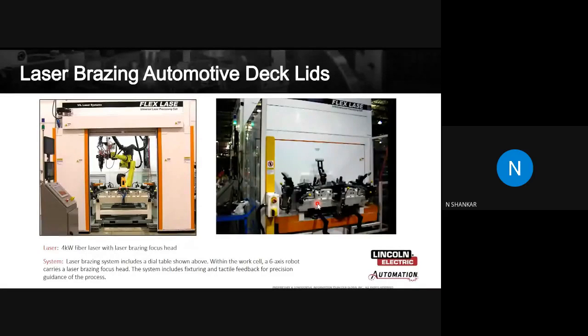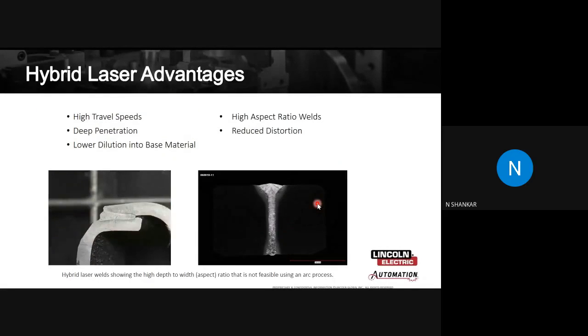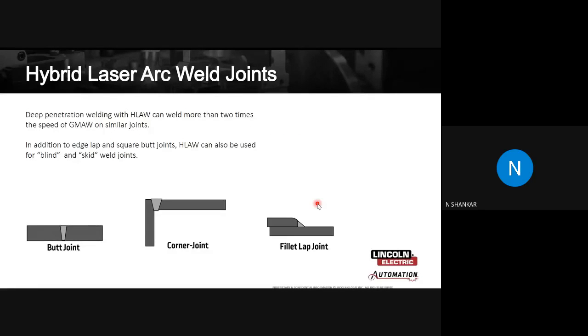Actually, here's another example. These hybrid lasers are advantageous for industries basically because they give very high travel speed, and very deep penetration based on your requirement, and give lower dilution into the base material, which means you have a shallow heat affected zone. You get the required strength, but you don't overdo the welding, because there's a limit to which you can control a GMAW process. This process is highly controllable, and therefore you have much better reduced distortion. Deep penetration welding is possible with hybrid laser arc welding.